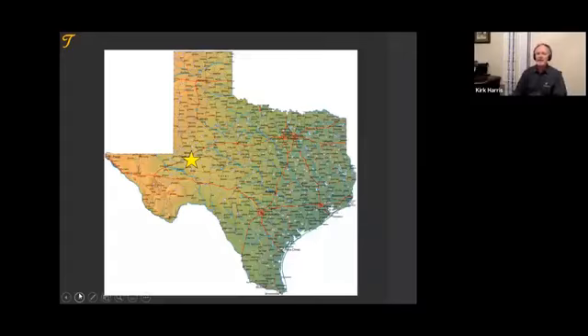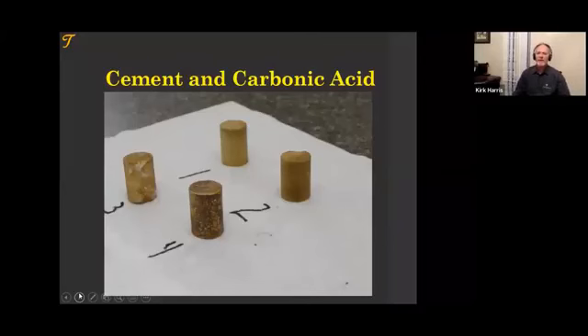In West Texas and up into New Mexico, formations there can be very corrosive, or we can be flooding with CO2, which can be corrosive. Our geothermal wells, our wells close to volcanoes, can be quite corrosive. So we test our cement for carbonic acid, and the cement's dissolved. There's a dissolution of the compounds in cement. So we test a lot with carbonic acid. Here, this work was done in Hobbs, New Mexico. And we see corrosion, the leaching out.